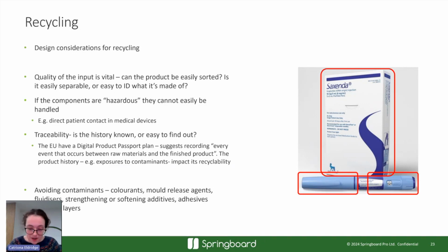The reason we care about this is we care about what's happened to the materials, because the quality of the input into our recycling processes defines the quality of the output. A particular example here would be limonene, which is a lemon scented flavouring. It's common in a lot of cleaning products. It's common in a surprising number of beauty products as well. And it dissolves quite neatly into most plastics. It's a fairly small molecule. It very happily wiggles in amongst other polymers.